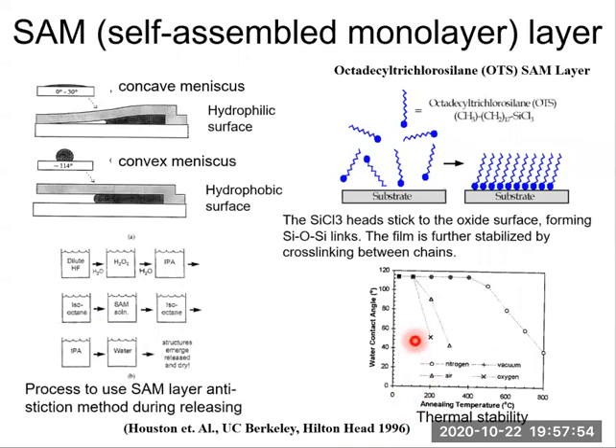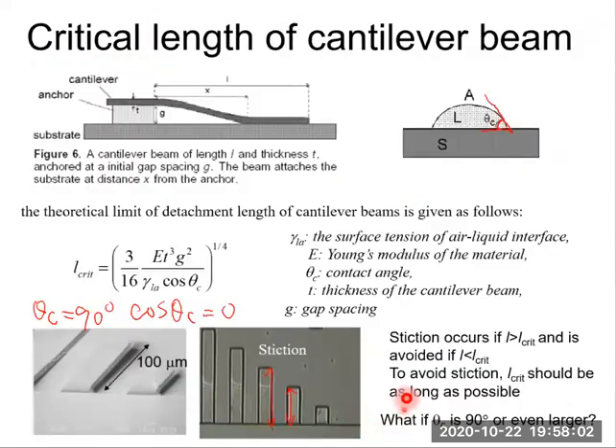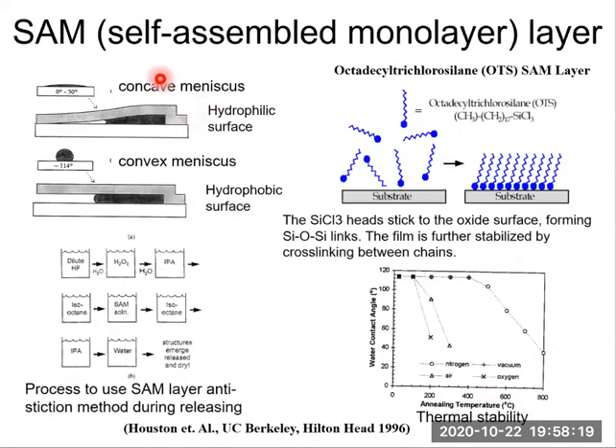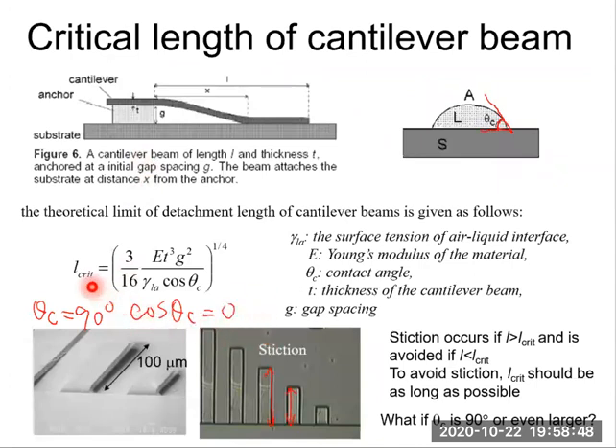This is the operating principle of using some layer to avoid stiction. But please know that we do not want stiction. When the cantilever sticks to the substrate, it's not functional. It cannot function as a sensor anymore. So we want to avoid stiction. We can use a self-assembled monolayer, a SAM layer, to avoid stiction. The operating principle is that the SAM layer can convert a hydrophilic surface to hydrophobic. Mathematically, L critical will be either infinite or does not exist.